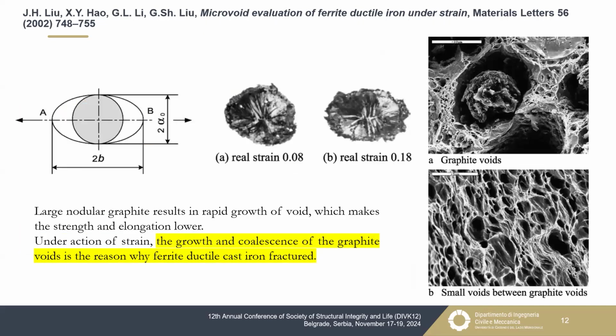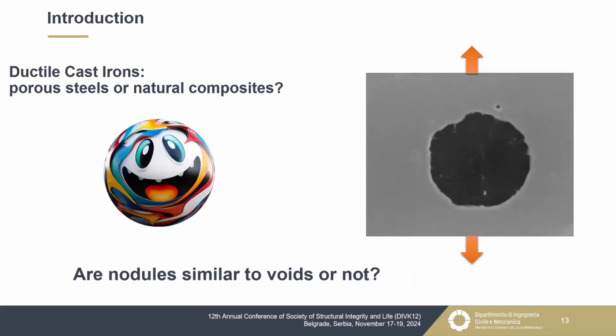Also, the problem of the dimension of these nodules was investigated, and large nodules were more critical. This is more or less evident. They were more critical from the point of view of damage in these alloys, and obviously larger nodules imply the rapid growth of voids with a decrease of strength and elongation, and the fracture of ferritic ductile cast iron was due to the coalescence of these voids.